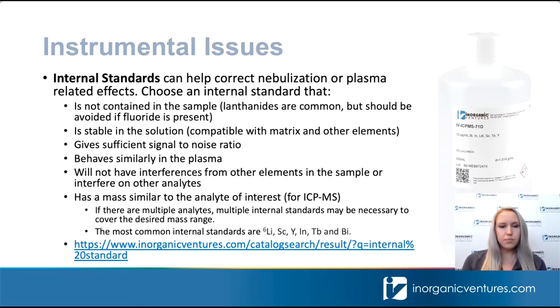So the most common internal standards used for mass spec, listed in order from lowest to highest mass, are lithium-6, scandium, yttrium, indium, terbium, and bismuth. I have an example over to the right-hand side of this slide of one of our stock internal standard solutions. This contains 10 ppm of each of those internal standards I just listed. But we do have several stock offerings for internal standards on our website, which I've linked below. And we can also create a custom internal standard made to your specifications for elements, concentrations, and solution matrix. So please feel free to reach out to us if you don't see what you're looking for on the website.